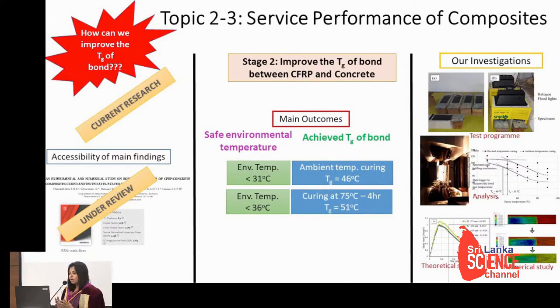So then we thought, what will happen if we apply the same technique for TG of bond between CFRP and concrete? Because in this case we have to select a safe environmental temperature, as it might adversely affect the concrete substrate. So we tried a similar approach and again we could find good results. So we can elevate the temperature of the CFRP concrete bond as well using this technique. That means this application will make a stable outdoor structure with good service performance.